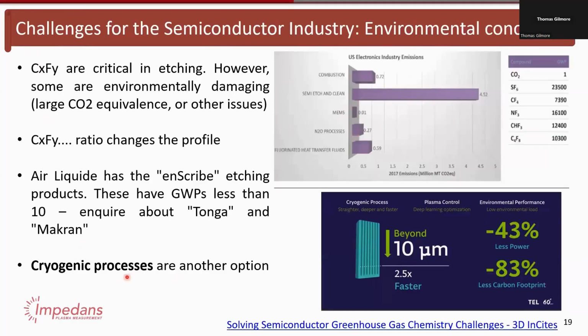I won't go into depth into this, but one other way of reducing this impact is by running some processes cryogenically. Now, strictly cryogenic is like minus 200 Celsius and below. But processes are being developed in the sort of minus 30 Celsius, minus 40 Celsius, which really help again with this sort of straight line etching going straight down. They tend to use less power, and they use less damaging gases. So maybe look into that if you haven't already. Cryogenic processes may be a way to go. Okay,